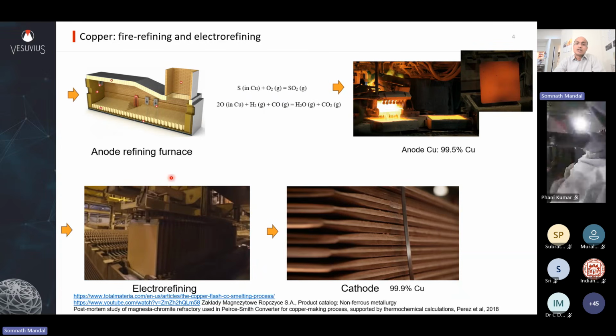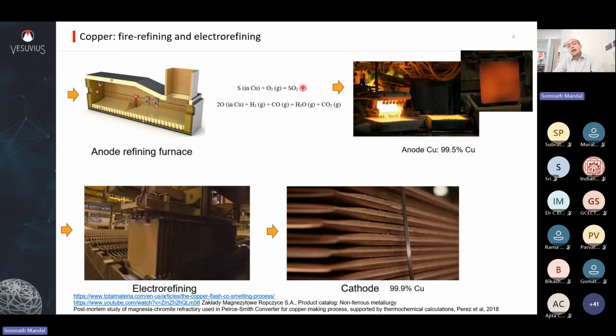It needs further processing. This blister copper is then charged into an anode refining furnace, and there are a few variants of this. Once it is in this furnace, first it is oxidized to remove the remaining sulfur. Again, it forms SO2 and goes out. By this process your sulfur is almost gone from your metal, but you end up with a lot of oxygen entrapped in your copper melt. This is then blown with natural gas, which reduces the excess oxygen, and now you get 99.5% purity anode grade copper. This is generally cast into anodes that are used later for electrolysis.